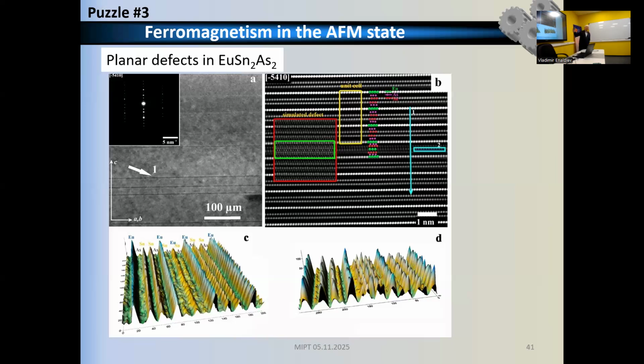Now instead, we have taken transmission electron microscopy, and you see here, this is not just artificially drawn, this is a result from measurement. There is something going on in this line. And this line is about 1 to 2% of the volume. And when you zoom in on what is going on here, you find that there are some planar defects, like that one enclosed by a rectangle, and they are missing tin layers. Instead, there can be seen an additional europium layer, and the distance is smaller by 20%.